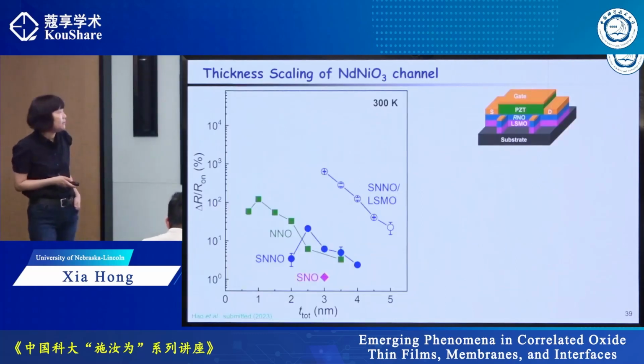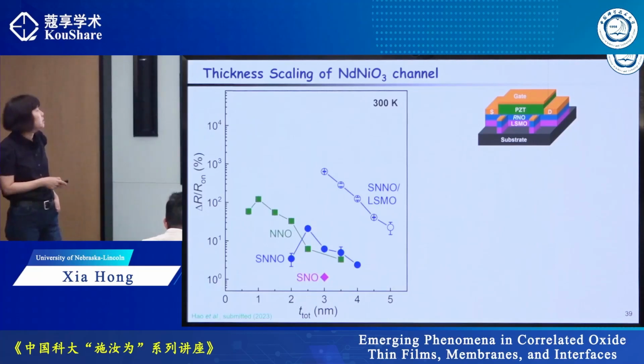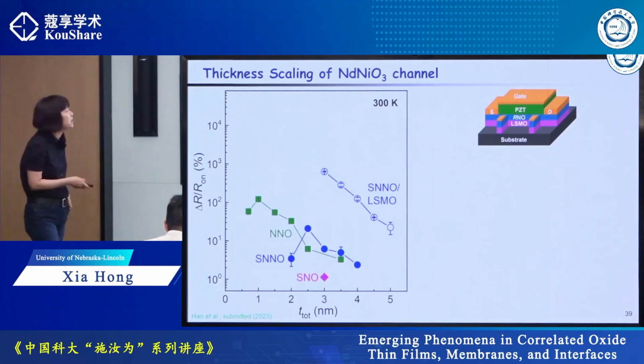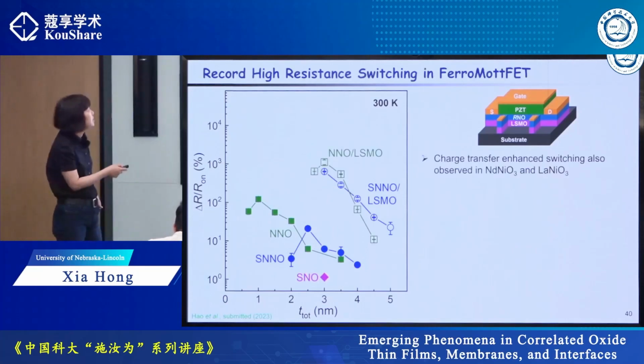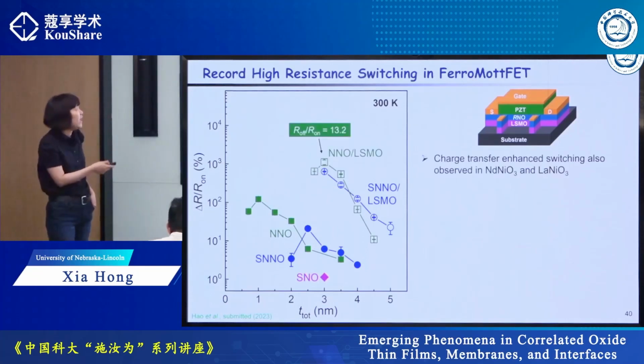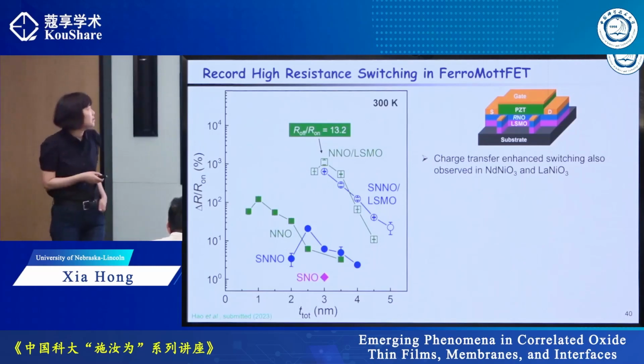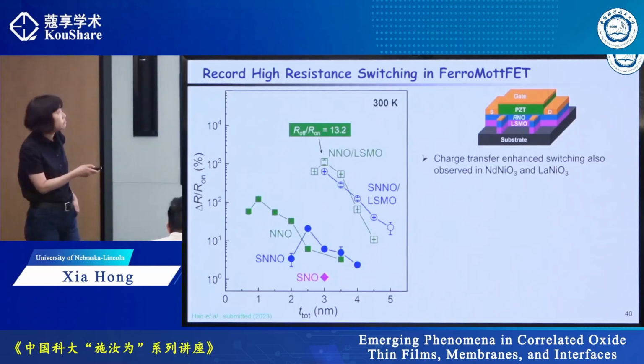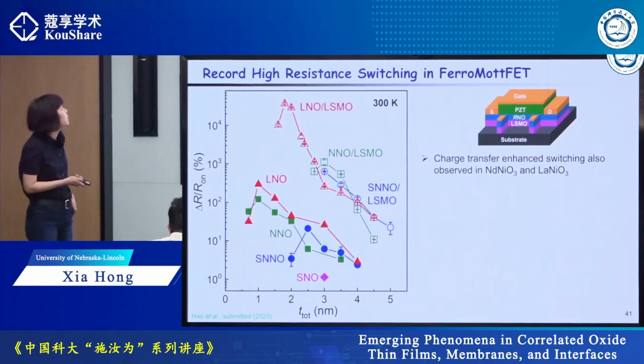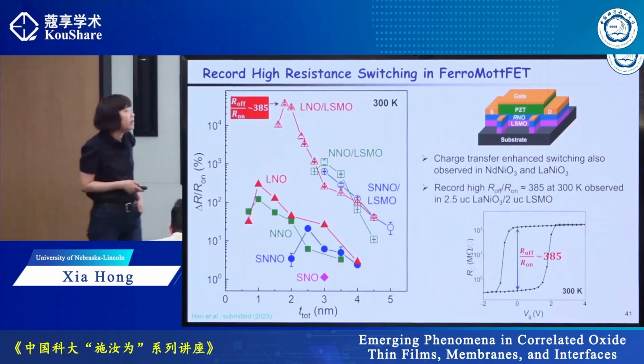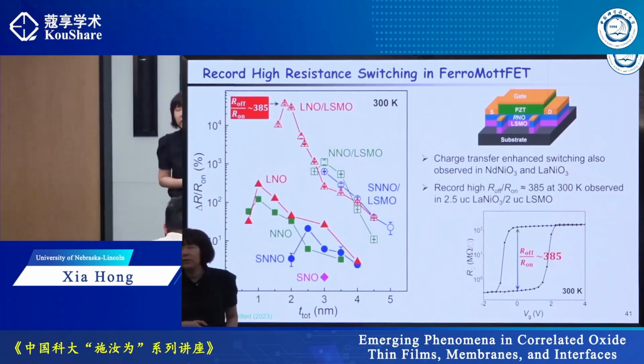So now we compare what we observed in all the nickelate combinations. So this is neodymium nickelate, and you can see that it gives a larger effect because neodymium nickelate has a smaller dead layer thickness. And next is LNO. This one actually gives a record high ratio of 385.